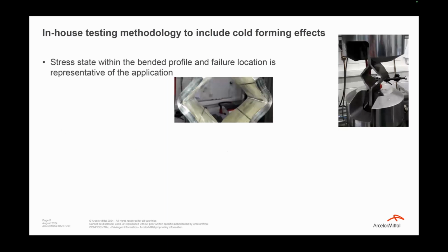So once you do the test and do the analysis, you'll see that the stress state in the bend profile and the failure location where the cracking happens is representative of the application. So in these profiles, under loading, if you have failure in the bend section, what you end up with is cracking starting at the inner radius and then propagating through the full thickness of the material.